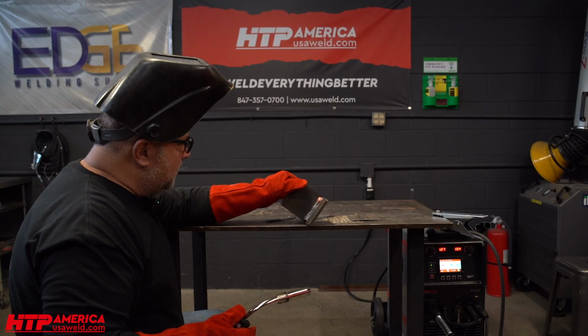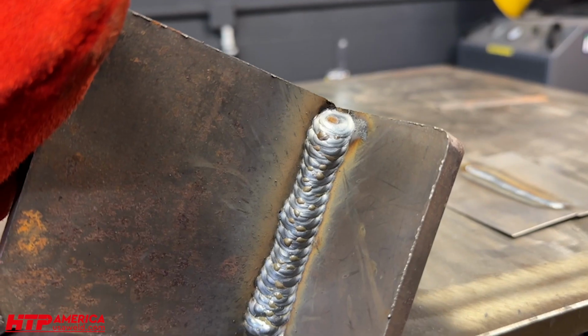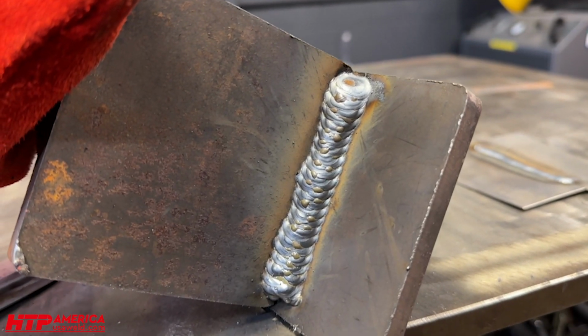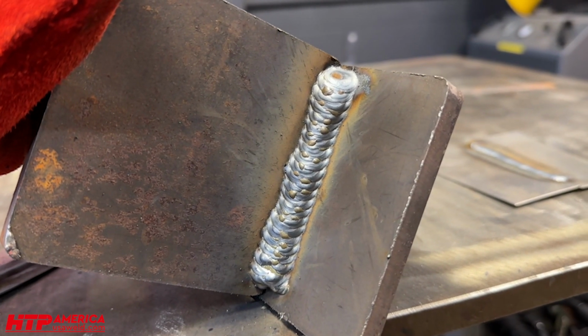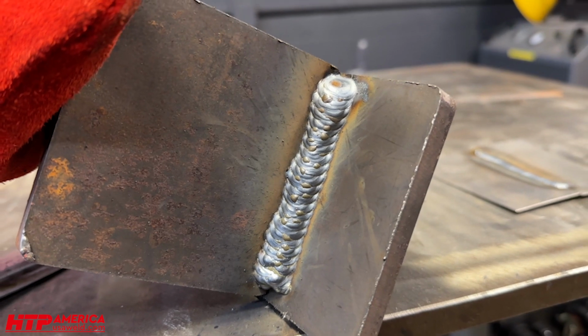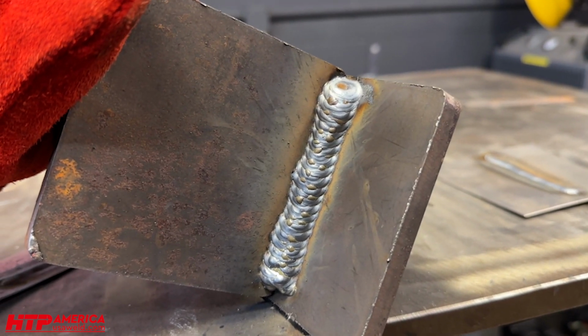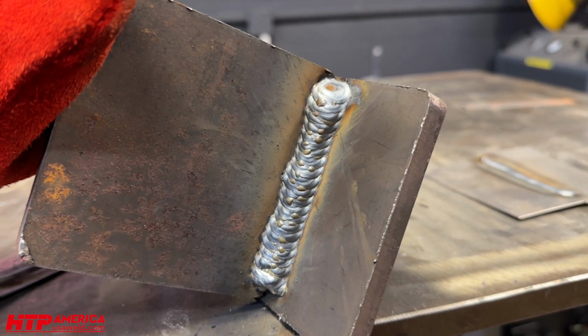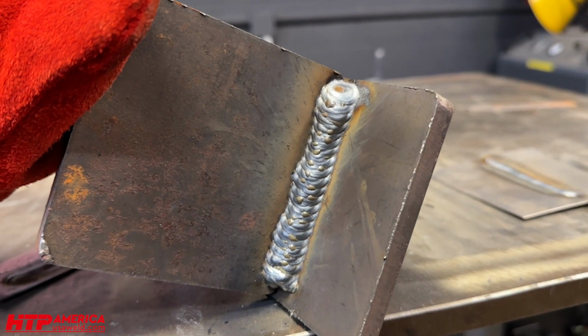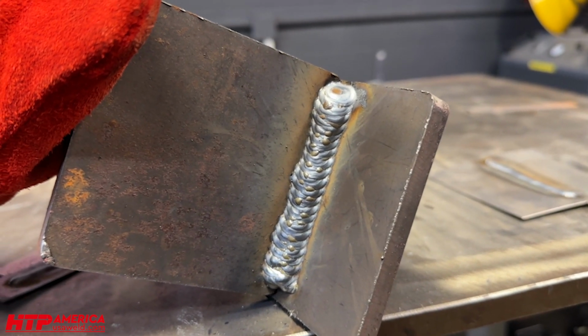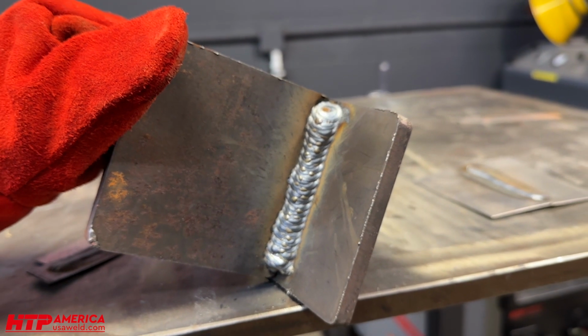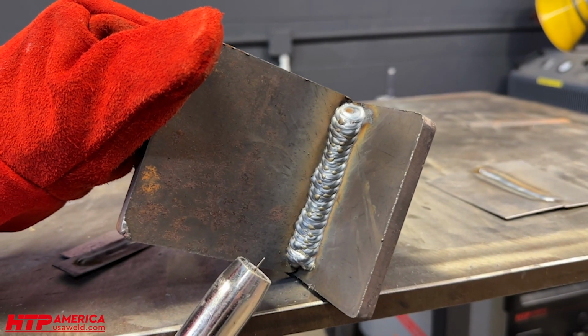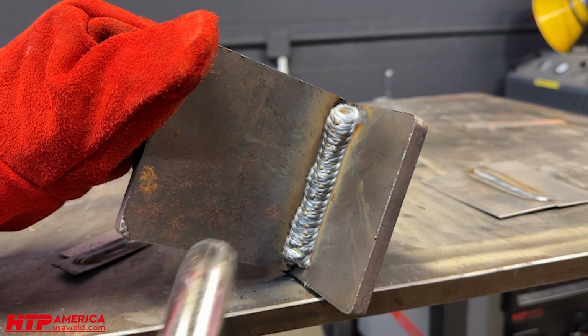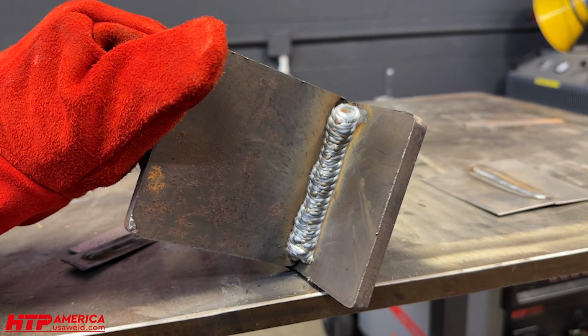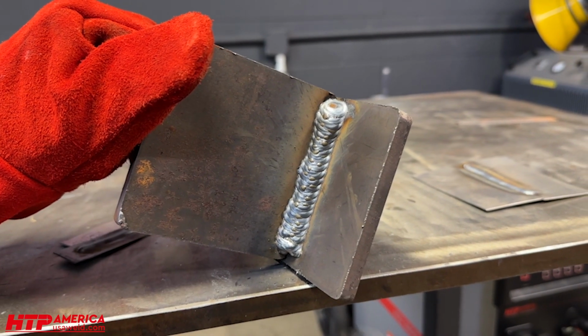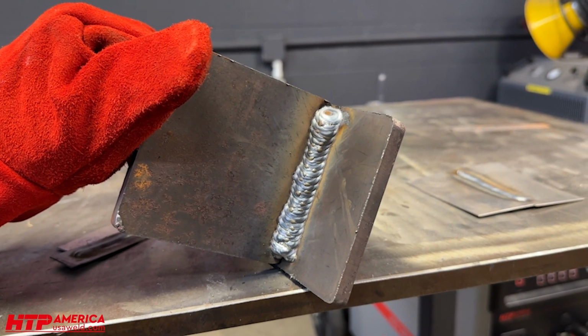So the second pass looks so much nicer now. So that just goes to show you that even though the machine says 10 gauge, just over 1/8 inch, that's about the most you want to weld vertical up. No matter how thick your material is, you may have to preheat a little bit. With that solid MIG wire, that .035 wire, the material just doesn't take any more liquid puddle without material rolling out and dropping off.